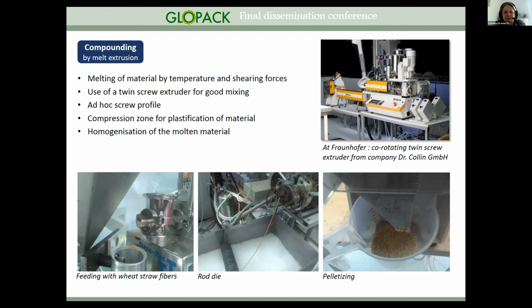Yes, and as Helen mentioned, the first step in the process chain in the project was this compounding step. During the compounding, the material is melted by temperature and shearing forces. Different compounders have been used in the project. You see some pictures here on the slide. For example, the twin screw extruder we used is good for a good mixing to integrate, for example, the nucleating agents or the fibers. The screw profile we used has different zones for plastification and homogenization of the material, so that we have a good mixture of the final material.